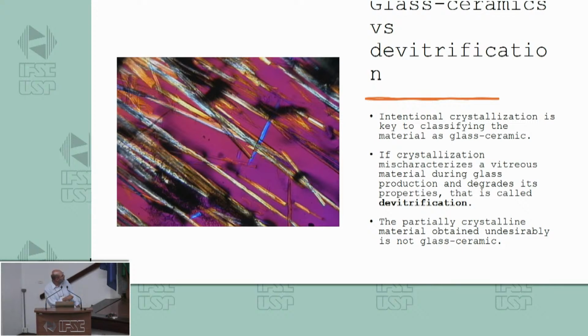I'm sorry, there is some problem here with the format, but there is also crystallization that is obtained when you're trying to make a glass, but by some process problem, the glass got crystallized as a defect. We call this defect devitrification, and this is not controlled crystallization. Actually, we have to dispose of the products that have this kind of defect. They have to be separated from what you're going to sell. And the name of this is devitrification, to separate it from crystallization by a controlled way to obtain glass ceramics. Okay? So it's not all the crystallization of glass that produces a glass ceramic.